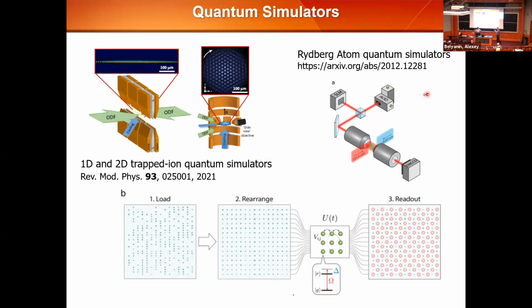Certainly. So the question is, can I use any super resolution technique to optically address individual cells? The answer is we're really at the hairy edge. I didn't show some of the images. If you have a homobilayer, you can actually construct Moiré cells that are 100 nanometers, so it is possible to address them individually. STED may not be the best answer because, as I understood, STED relies on nonlinear optics, where you're saturating part of the beams, so you still have light falling on other unit cells. It's really tantalizingly close. You should be able to address it. There's what's called a light shield technique. Basically people are already creating these super resolution arrays of optical beams. If you can overlay them with the Moiré, you can potentially do that. With enough determination, I think it can be done.